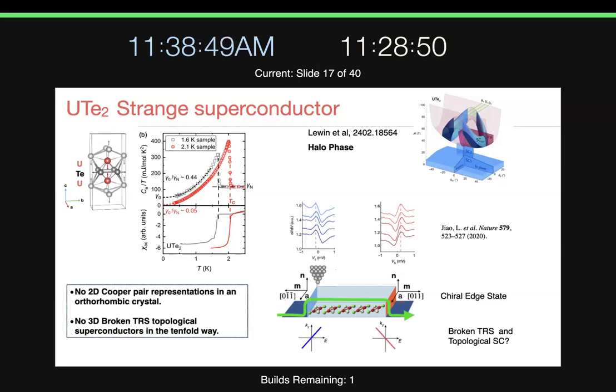So the material is three-dimensional? Yes. Okay, and then they're doing STM on a top surface. Unfortunately, there's only one surface that actually cleaves. Okay, and their claim is that maybe on that surface you see something. Yes, and there are counterclaims to this, as you can imagine, in any experimental work; there are different points of view. If you're seeing a correlation on the boundary... Well, it's on a surface. The interpretation is that there is a current running along the surface, and that you can see it at these step edges.